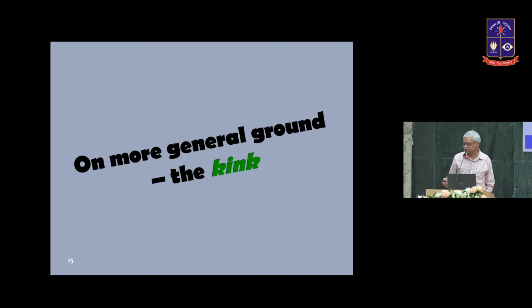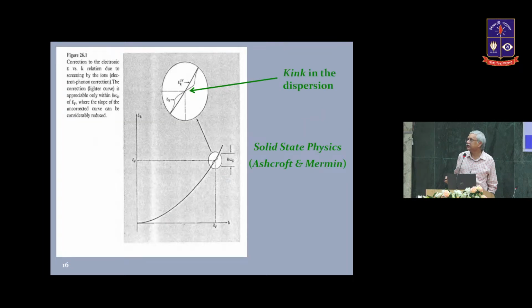There is another indication of coupling of electrons with some bosonic degrees of freedom, and it comes from the electronic dispersion relation. There is a kink, and this is clearly shown in that very good textbook, Solid-State Physics by Ashcroft and Mermin. You can see it here. This is the electronic dispersion line, this one in the middle. But once it becomes distorted like this, it is a clear indication that the velocity of the quasi-particles, say the electrons, which we have in the periodic lattice, is changing. And what is bringing out this change? This is the coupling between electrons and some bosonic degrees of freedom. The energy dispersion becomes distorted when it couples to bosonic degrees of freedom. And for an electron phonon system, the region over which you can see the distortion gives a measure of the energy of the bosons that is affecting this dispersion.